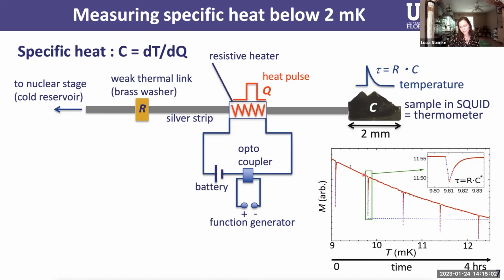And then in regular intervals of about an hour, we apply short heat pulses to the sample that just briefly change its temperature a bit more. And then we watch the thermal relaxation. And now importantly, this is not measuring temperature, this is measuring magnetization. But because we're looking at the magnetic response to a thermal excitation, the time constant is thermal in nature. And from this time constant, using the thermal resistivity of a weak link to our nuclear stage, we can extract the specific heat.